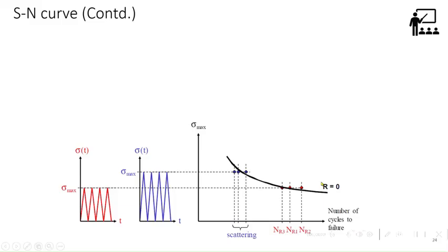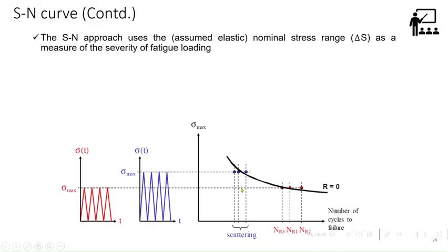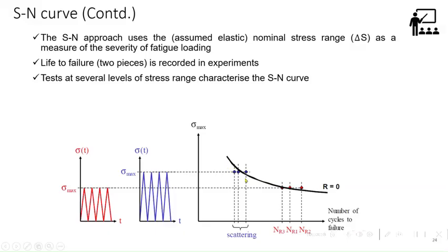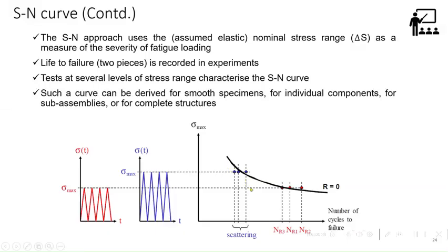So to generate SN curve, what he did is the usual way: you take a specimen, subject it to certain stress ratio and cycle it, and note down how many number of cycles it takes to failure, and join those points to get a SN curve. So this example says R is equal to 0. In 1 point, sigma max, you are taking red color.